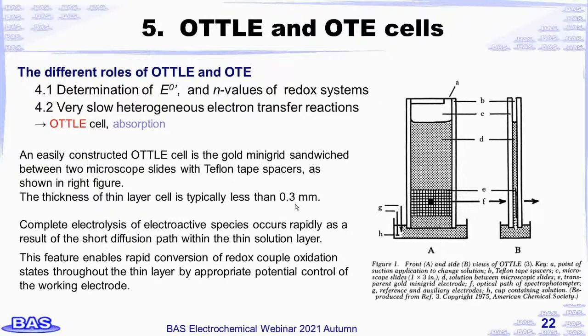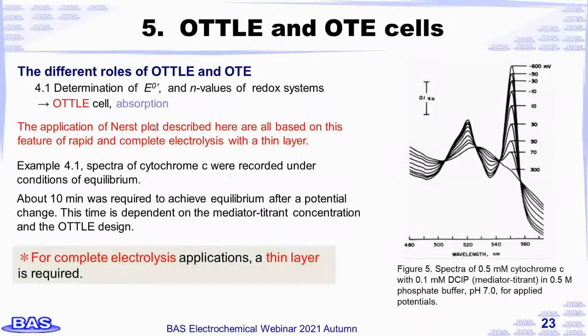Complete electrolysis of electroactive species occurs rapidly as a result of the short diffusion path within the thin solution layer. This feature enables rapid conversion of redox couple oxidation states throughout the thin layer by appropriate potential control of the working electrode. The application of the Nernst plot described here is all based on this feature of rapid and complete electrolysis with a thin layer. Example 4.1. Spectra of cytochrome c were recorded under conditions of equilibrium.